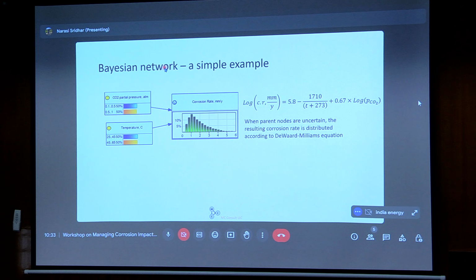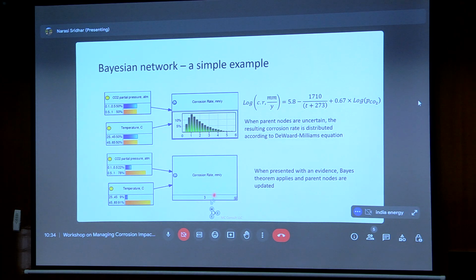So to do that, a Bayesian network is a good way to do, and I'm giving you a very simple example here. So if you have a CO2 partial pressure, but you don't know what the value is, so you assign coin toss, 50%, it's 0.1 to 0.5 atmospheres, and 50% is 0.5 to 1 atmosphere. And you don't know the temperature, and again, you assign a probability, and it gives you a probability distribution. And here I've used a well-known de Waard-Milliams equation that equates corrosion rate to partial pressure of CO2 and temperature. Now, the advantage of a Bayesian network is, what if you know the corrosion rate through inspection? So now you know that the corrosion rate, it says, well, most likely your partial pressure of CO2 is high, and there is also a good likelihood that the temperature is high as well. So basically, Bayesian network allows you to update your input factors based on your knowledge, which is based on the data, which is inspection data.